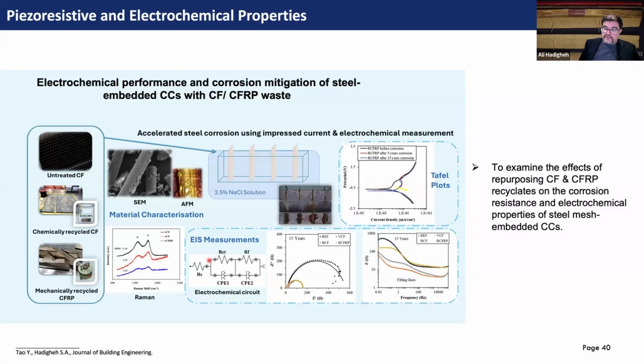One of the things we always look at, for example, is mechanical properties or some of the durability properties of these concretes with waste materials. But specifically for the case of carbon fiber and CFRP in concrete, we need to be very careful about corrosion, because usually to avoid corrosion, you need high resistivity inside concrete. But when you add carbon fiber, a carbon-based material, into your cementitious material, you are reducing the resistivity. So you are increasing the potential for corrosion. That's why we did this research.